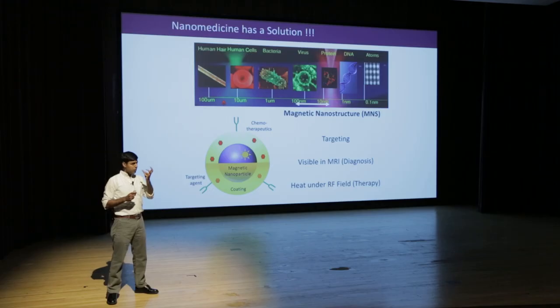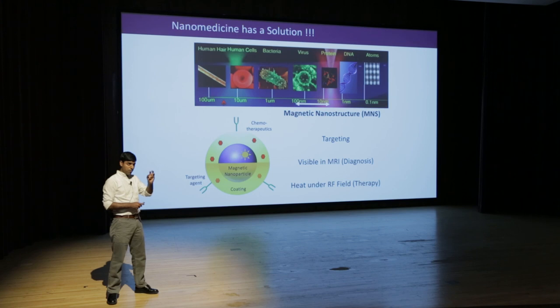The way it should work is that they enter inside the cancer cell and destroy it without affecting normal cells. In our lab we developed this magnetic nanostructure. It's like a regular magnet, but if you keep reducing the size down to the nanoscale level, it becomes a magnetic nanostructure with distinct unique properties. These particles have a special design: in the core there is a small magnet, then a coating that holds anti-cancer drugs, and finally receptor-like antennas on the surface.